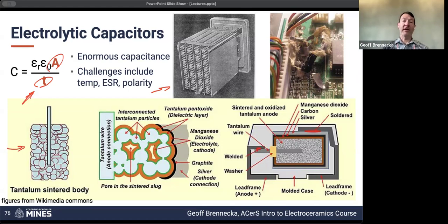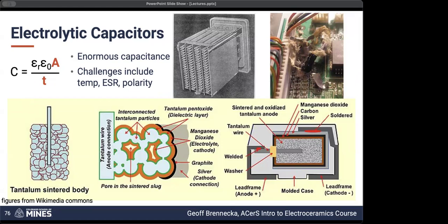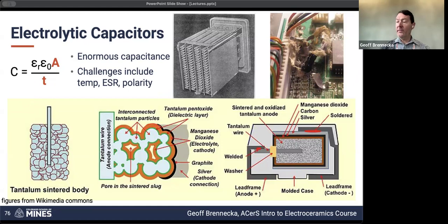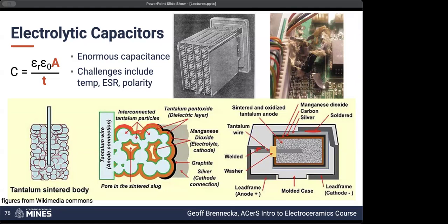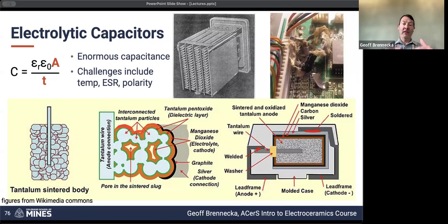The nice thing about electrolytic capacitors is that because of the field distribution that occurs in this process, you're going to grow a conformal layer of the oxide. So if one region happens to build up a little bit thicker, then that is going to drop a little bit less field. And so you'll end up putting more field and more current through a thinner region, which basically self-heals and self-limits that process so that you can anodize a nice continuous, very reliable thickness in your material.